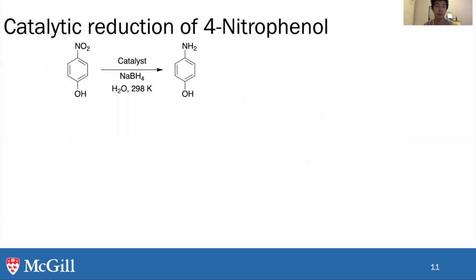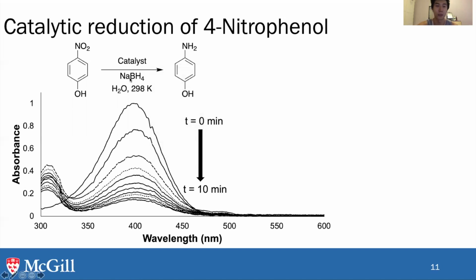And so with this material, we wanted to see how it can be used as a catalyst in itself. One of the main reactions we use is the catalytic reduction of 4-nitrophenol. We want to focus on this because one, it's a very simple reaction. It's in water. It takes less than 10 minutes to do, as well as it can be easily monitored through UV-vis spectroscopy. So we can see here, this peak at 400 nanometers corresponds to the nitrophenolate starting reactant. And as the reaction goes and product forms, this peak decreases, while this peak attributed to the 4-aminophenol increases.